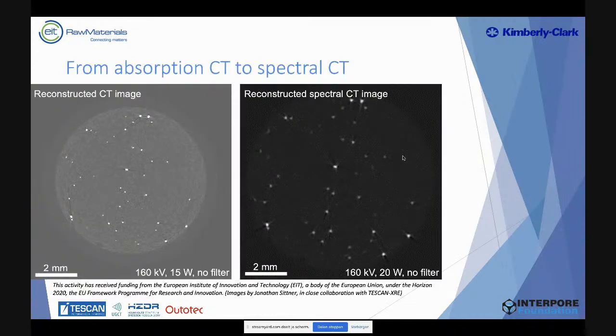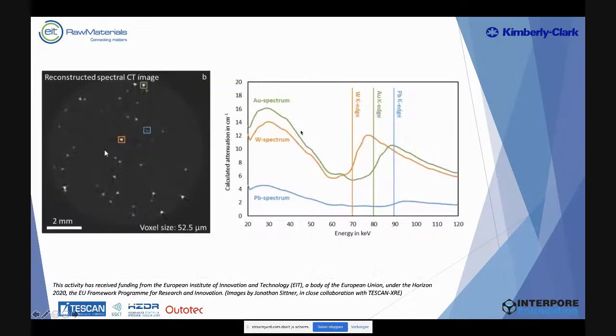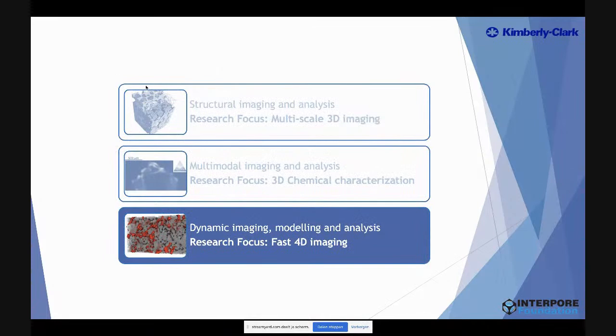If you do spectral CT, the resolution is a little bit lower, but you can also identify the same grains. And if you then look at the spectrum that was detected by those detectors, you can distinguish the different grains, and you can say, okay, this one is the lead, this one is the tungsten, and this one is the gold sample. So this allows you to get 3D chemical information for certain minerals and elements. This work is ongoing in order to help us understand the chemical composition of materials.